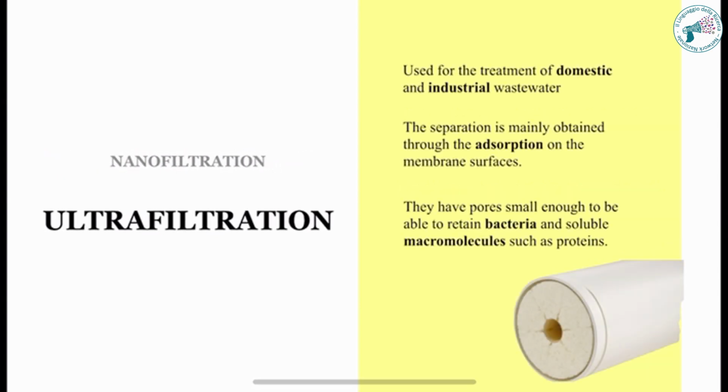Ultrafiltration refers to membranes that fall within the pore range of 0.01 µm to 0.1 µm. They have pores small enough to be able to retain, in addition to large particles and microorganisms, also bacteria and soluble macromolecules such as proteins by exerting higher pressures.